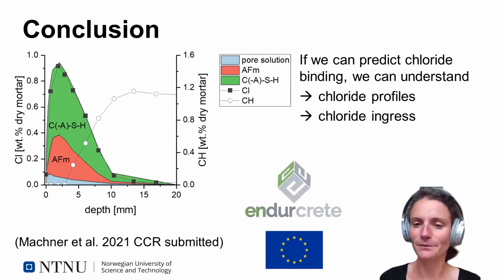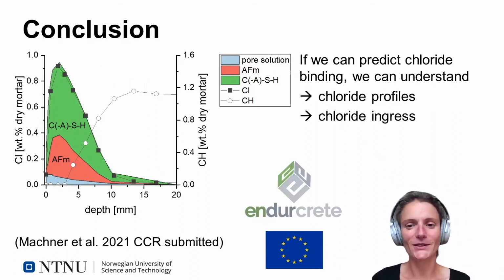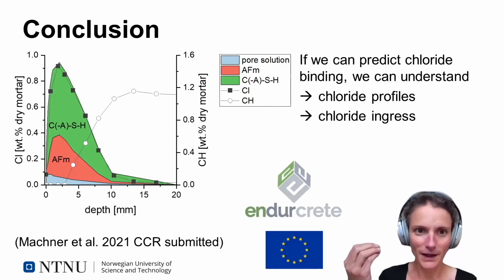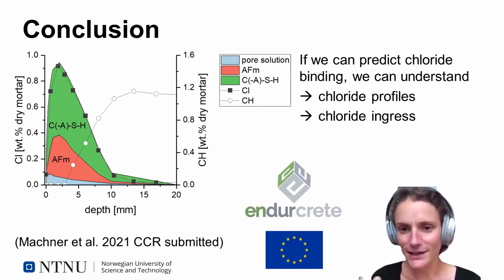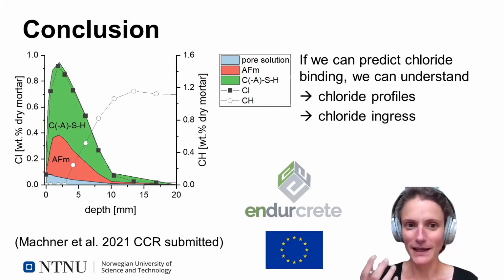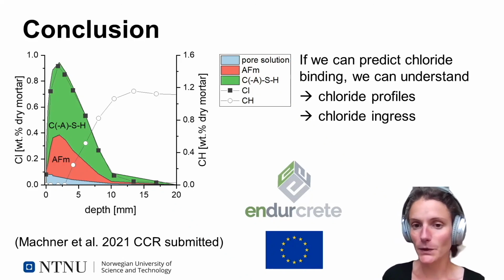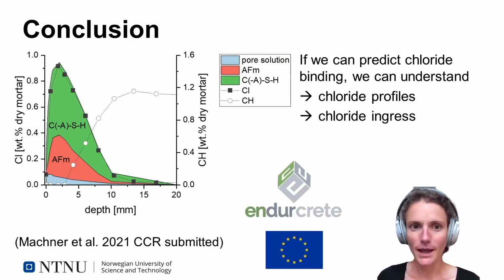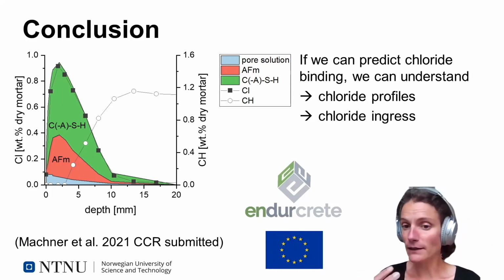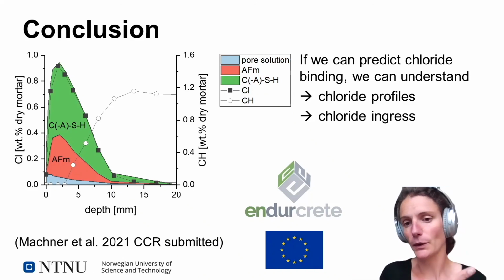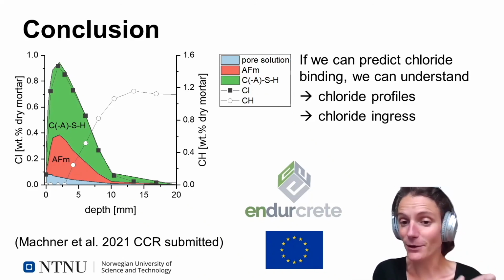So to conclude my talk, where do we actually want to end up? What is the ultimate goal? This figure is a little bit an illustration of it. It's not fully there, but close to it. It's work done by Alisa Machner in her postdoc within the Chloride project. And what she did here is she determined the amount of AFm and CSH using thermodynamic modeling, and she measured with SEM-EDS the chloride content in these phases. And when she combined these two, she was actually able to reproduce the shape of the chloride profile of the mortar where the chlorides had ingressed.